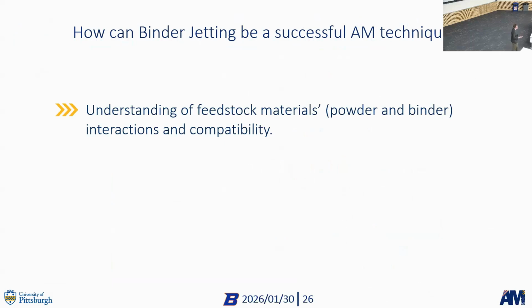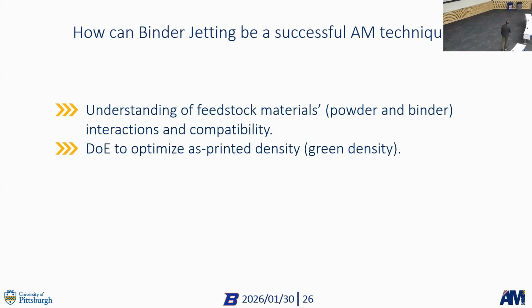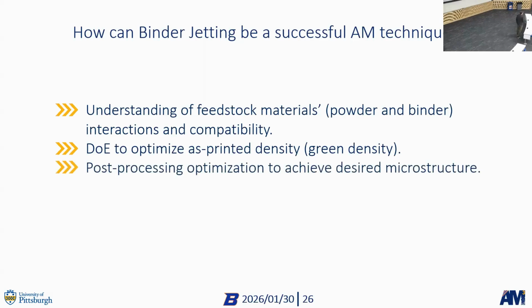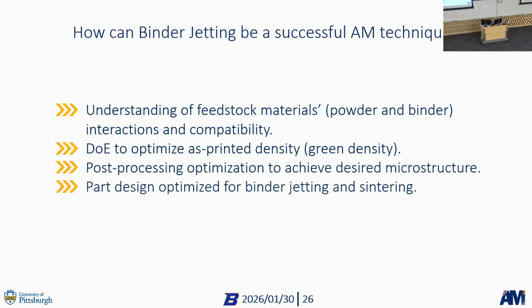Okay, so how can binder jetting be a successful additive manufacturing technique? Well, we need to understand the feedstock materials compatibility and interaction, so powder and binder. We need to optimize the as printed green density because that translates into the sinter density, right? And the microstructure. And then we need to also, and we didn't talk about that, optimize the design as well. Because if you have a ginormous part that is all solid, it's very difficult to get the binder out, right, from the center. So you need to design for binder jetting, basically.